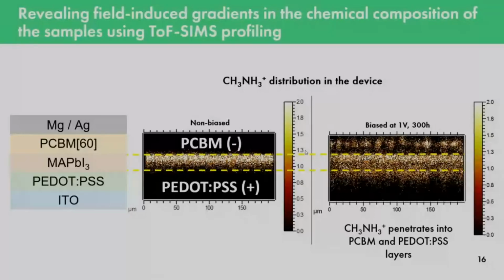Okay, as I remember, you found that the methylammonium cation, after applying 1 volt, migrates both to the PCBM side and also to the PEDOT:PSS side. And you know that perovskite materials can exhibit cation conductivity. So it means if the cation is removed, the rest of the framework should be negatively charged.